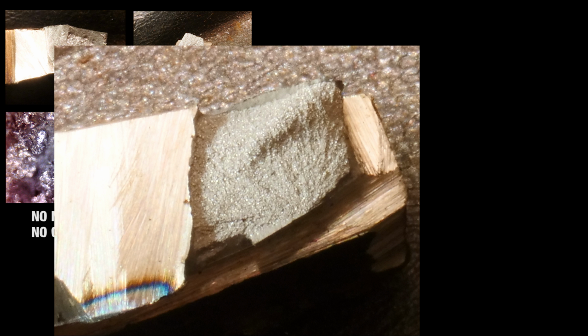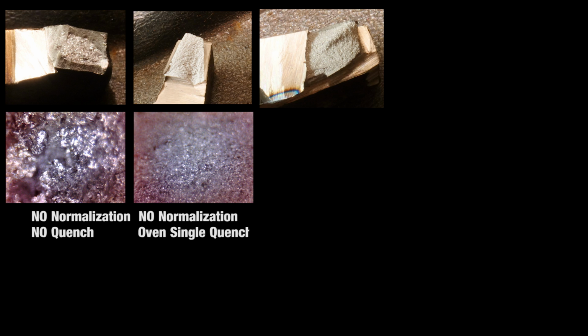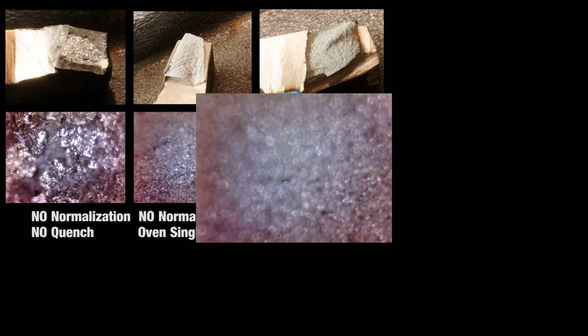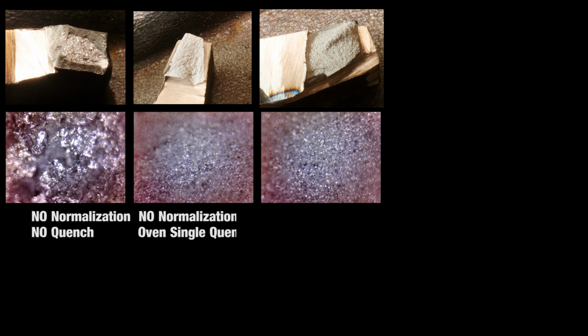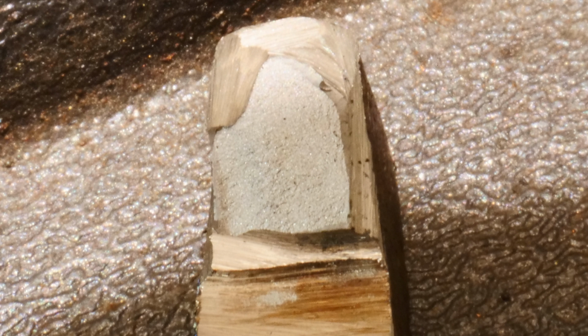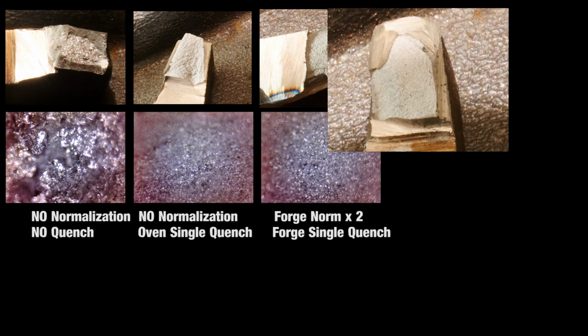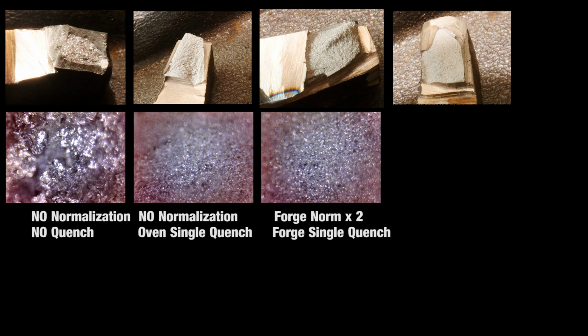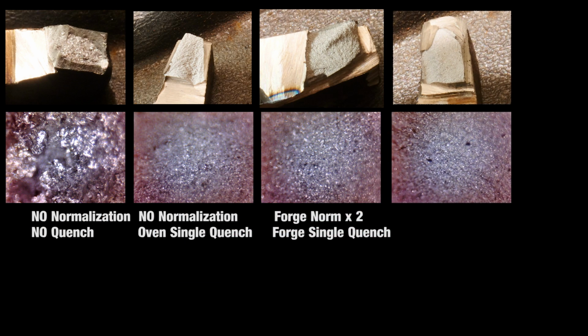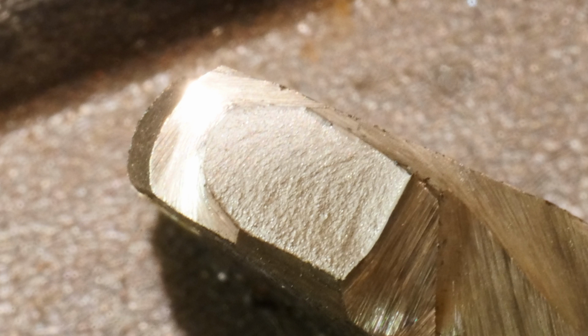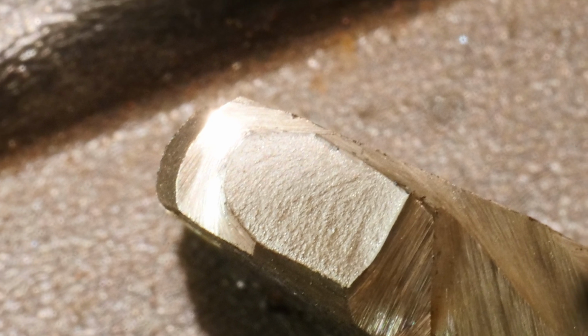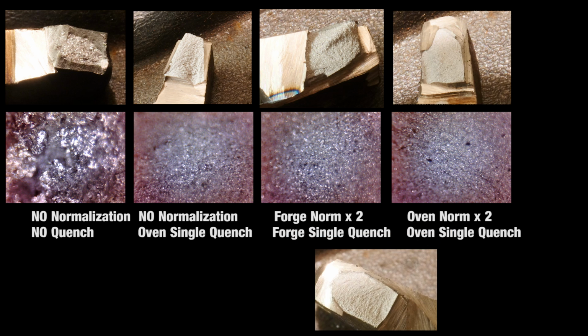Here's no normalization and a quench from an oven, so temperature controlled. It's actually pretty good. Our typical forgeside quench there with 2 normalization cycles and a single quench. Followed by oven normalization and oven quench. And last and most interesting, the triple quench.